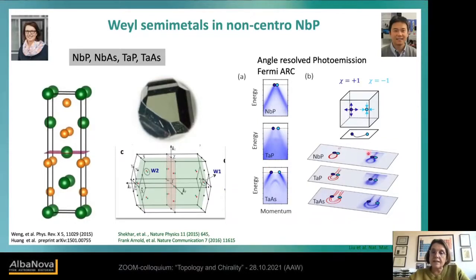So the first proof is, can we see these Fermi arcs? This was the first experiment all the groups did. And we did this also for all the 3 compounds we have grown. And this is a density functional calculation, and this is an experimental measurement. And you see that you have quite a good agreement.